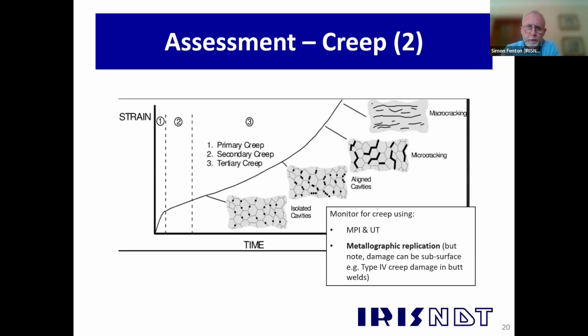So this is another view of that creep curve showing this progression of damage. So you've got in the bottom left there isolated cavities forming on the grain boundaries out of the secondary stage into the tertiary stage. Those cavities are then starting to align themselves on the boundaries, eventually forming micro cracks and then joining to form macro cracks. It's only at that macro cracking stage that we can use conventional NDT to find these cracks, this damage. Up to macro cracking, we need surface replication to find the damage.